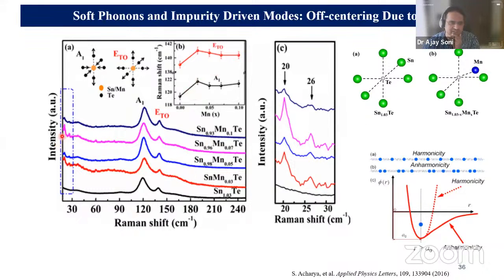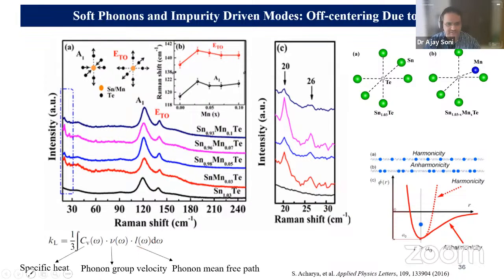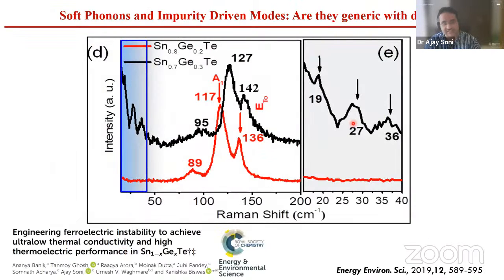But the interesting part here is at the low frequency range, where you can see that this is the pure compound and this is the doped compound. So you have new modes which are coming up, and these new modes are coming up because of the change in the inversion symmetry, the anharmonicity which is created, and that actually creates the phonon scattering center, and that can reduce the lattice thermal conductivity in this material. So you actually are targeting the phonon group velocity in this material, and this is generic actually.